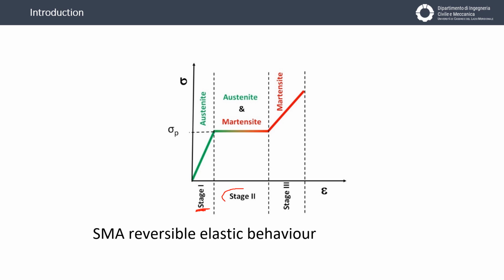Then we have a second stage, which is similar to a plateau, and sometimes is schematized as this. In this stage, we have a changing of microstructure from austenite to martensite. And then over this stage, we have the third stage, characterized by a slope different to the slope of the first stage. This slope is the slope of the martensite.